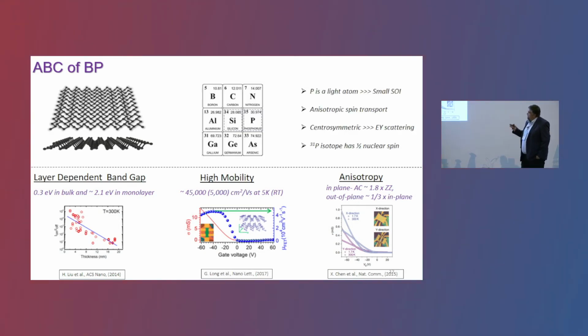Why we mainly got interested in this material is because, as you can see on the periodic table, the phosphorus atom is a neighbor to silicon, which is kind of the star material for spin transport. It has light atoms, so spin-orbit coupling should be small. And also, it's a centrosymmetric material, meaning that you would expect an Elliott-Yafet type spin scattering mechanism, which suggests that if you have higher mobilities, then you would have much higher spin transport properties.